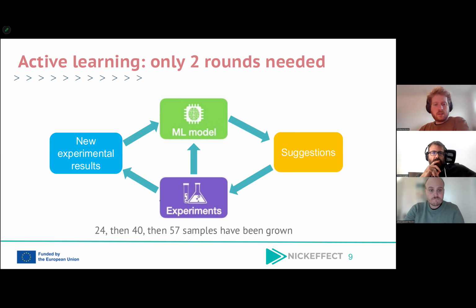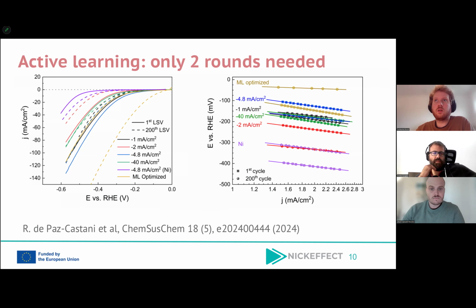And in this small project, we started with 24 samples, 24 films that had been deposited. Then we suggested 16 of them, 16 new parameters. So we had 40 after this step, after this first round of active learning. And then we suggested 17 more. So we had, in the end, 57 samples that had been deposited by UAB. And among these 17 samples, we had one that was actually performing the best among all of the others.